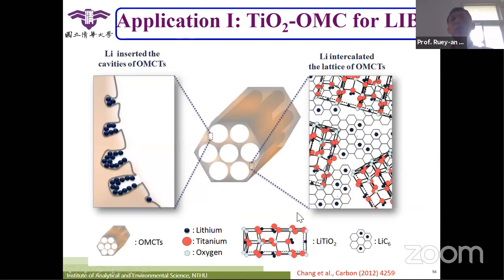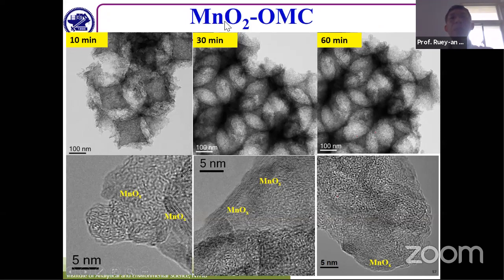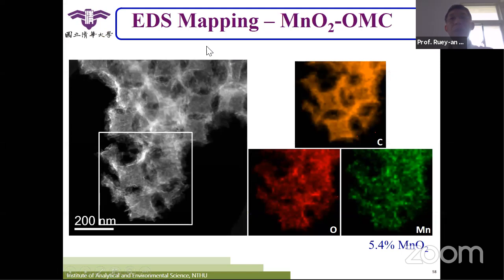So we use this for lithium batteries. We have the highly ordered structure, and it has pores, so the lithium can be stored in the pores. When you charge and discharge, the lithium ions get inside and then get outside. They can go into the TiO2 here, or into the carbon. We can put MnO2 inside here.